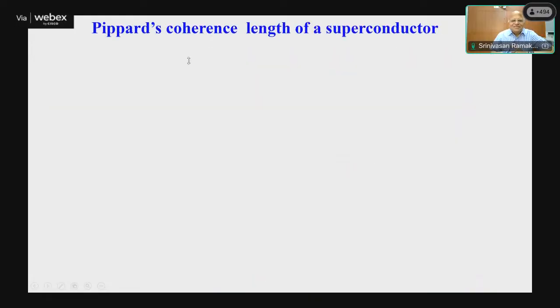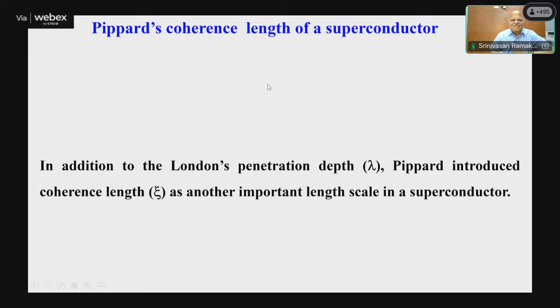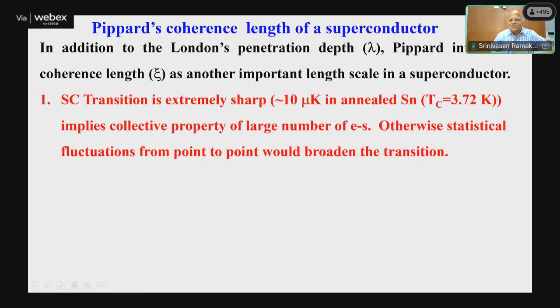So Pippard said, no, no, London's penetration depth lambda is only one of the characteristic lengths. He introduced another important length called the coherence length. Why did he do that? He said the superconducting transitions are extremely sharp. It is 10 microkelvin for a material like tin. It's 3.72 K plus or minus 10 microkelvin. It's that sharp. So it has to be a collective property of a large number of electrons. Otherwise, statistical fluctuation from point to point would broaden this transition. You would not get such a sharp transition.